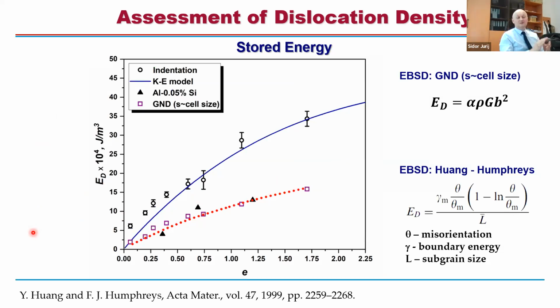Again, once you know the dislocation density, you can easily calculate the stored energy, or the energy which is stored during plastic deformation. Here you have the simple formula, alpha rho G b squared. So rho you either estimate by the model or by indentation or by other techniques, or simply you take GNDs from EBSD and multiply them roughly by 2, and it will also give you a very good guess, right? But not at very small strains; after 30–40% thickness reduction, we observe this saturation, right? Okay, and here is our Kubin-Estrin or modified Kubin-Estrin model. So we calculated the stored energy by the model, putting in rho which comes from the model, and then again by indentation, and again we observed quite good correspondence.